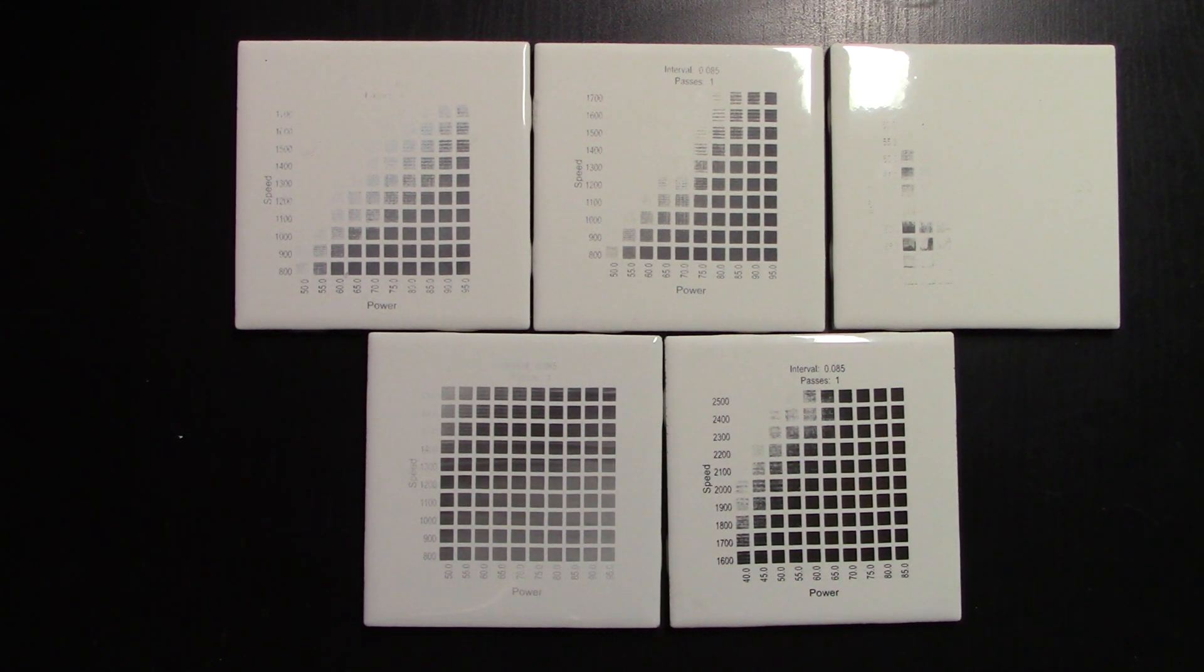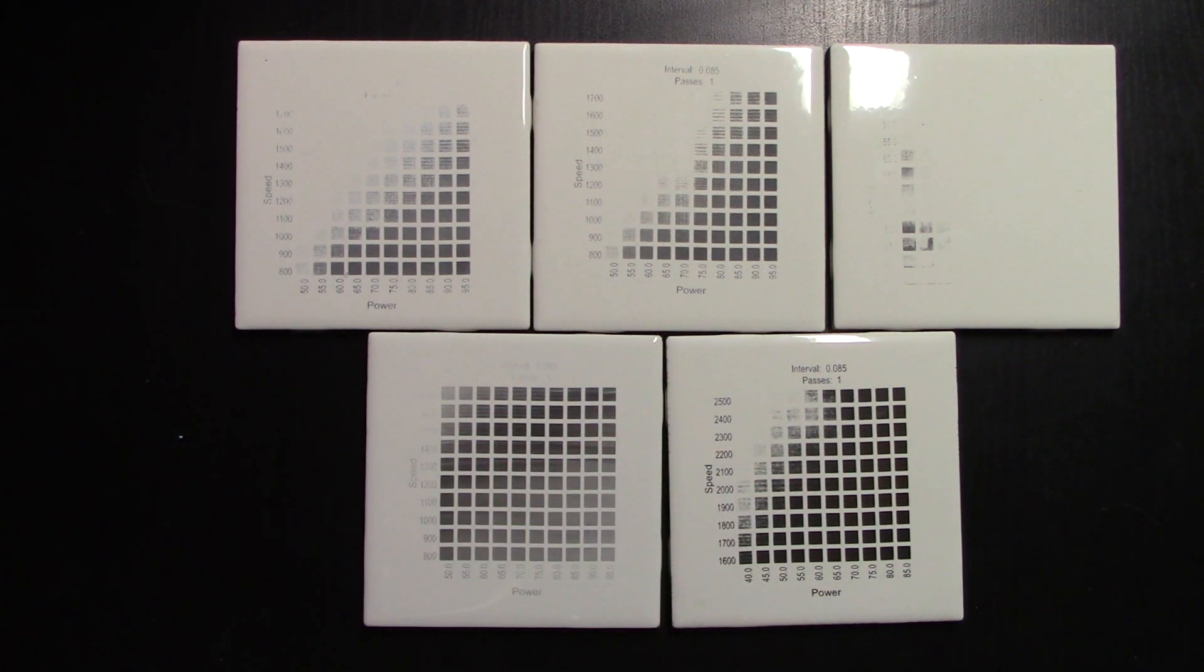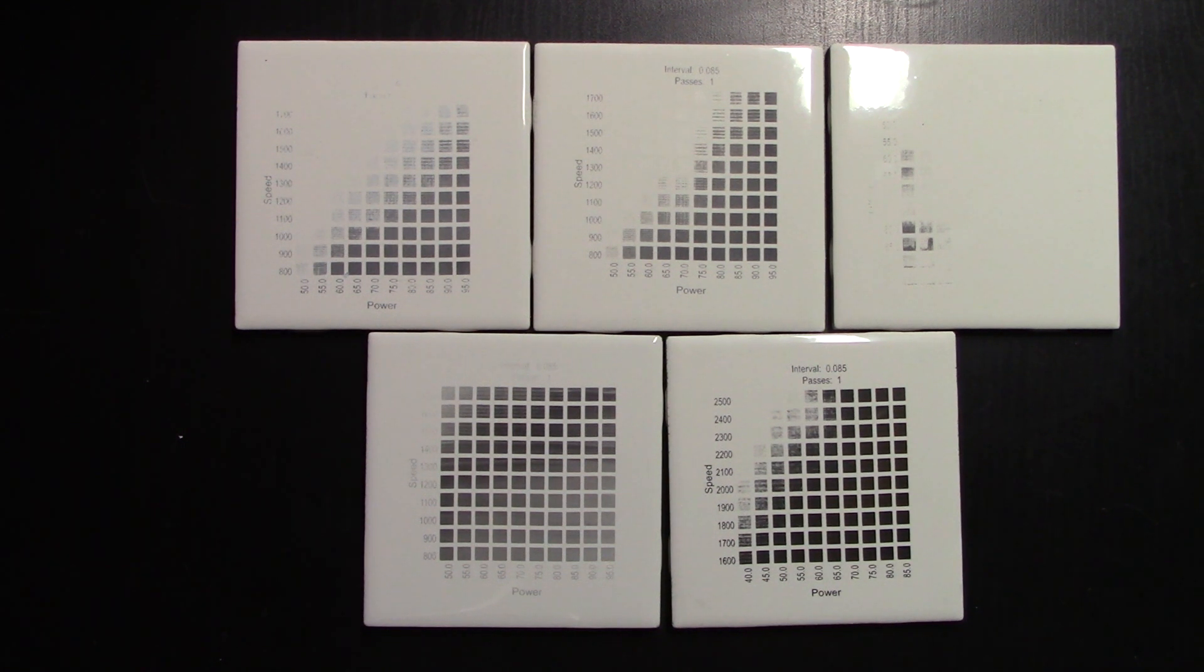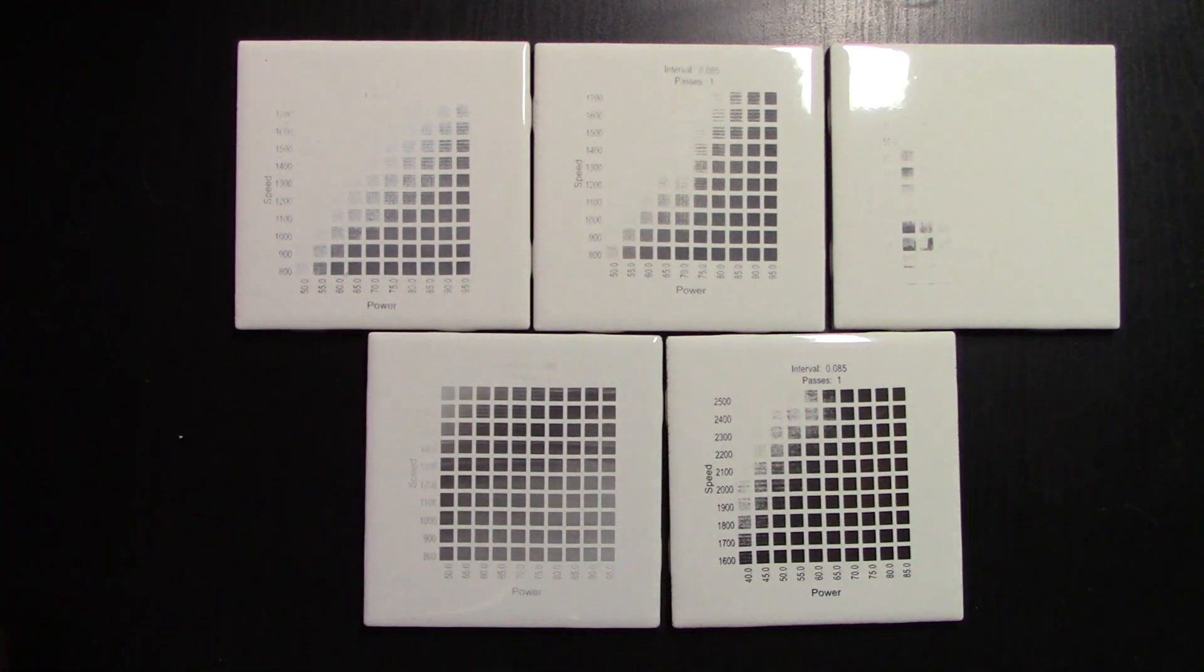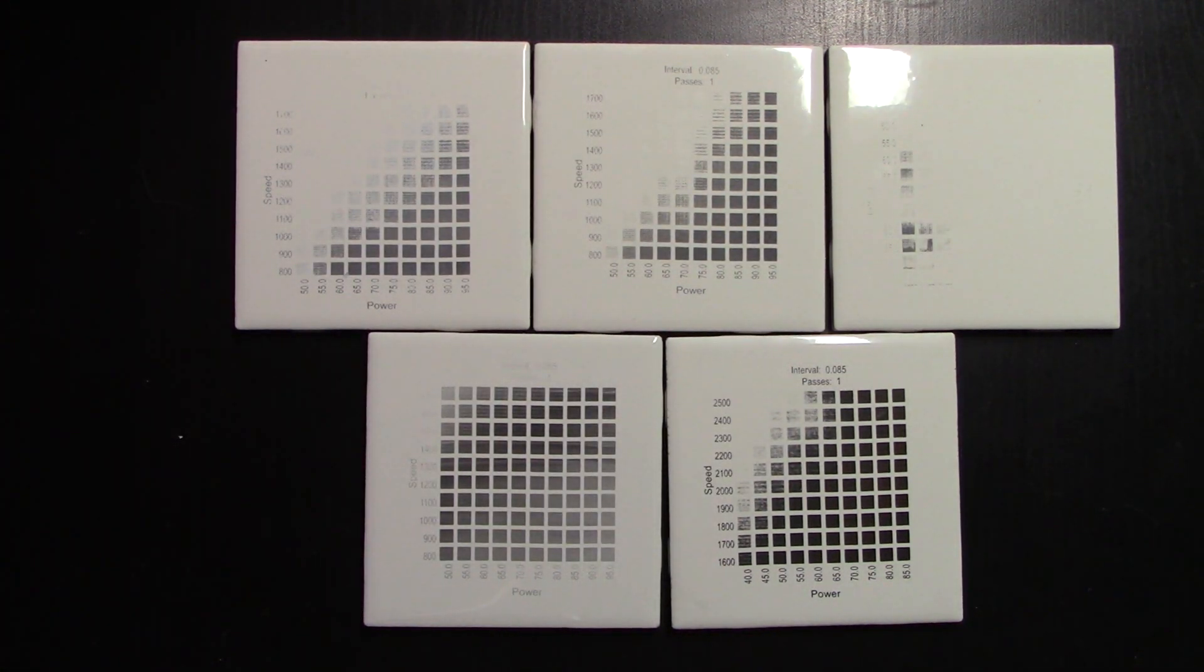So between these products, CGC, I think is definitely the winner. I'll probably switch to that instead of using the white paint, just because of the inconsistencies with using the white paint. You have to be very consistent on how much paint you put on. And that can be kind of tricky. You still have to be consistent with the cold galvanizing compound. It's just easier to see that gray on white. So you know, you've gotten a nice even coat versus with the white paint, you could easily miss a spot and not notice it. I think the two passes of a light coat worked pretty well. I might've been able to put just a little bit more on and that would have worked out pretty well. The two heavy coats definitely was too much.